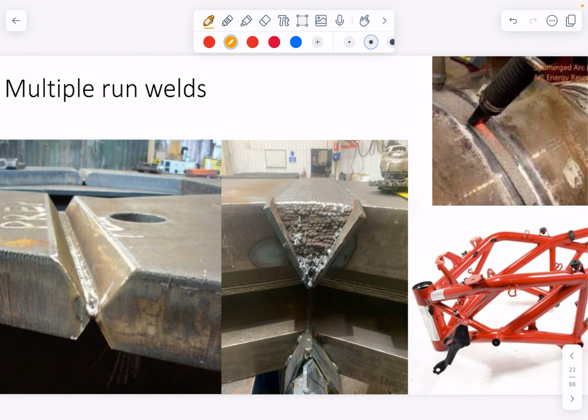I mentioned multiple run welds, and these two images are a great example. So we've got a fairly thick plate here. You're not going to weld that in one pass. Now here they've got what's called a root run down, so somebody's run along and put the first bead of weld, and you can see the heat bloom on that side at least where it's blown through or blown the heat into the job. The next image across, you can see these plates that are tacked on to the edge. They're fairly little thin plates tacked onto this big fat heavy plate, and you can see all of the beads of weld. Now I've got no idea how thick this plate is.